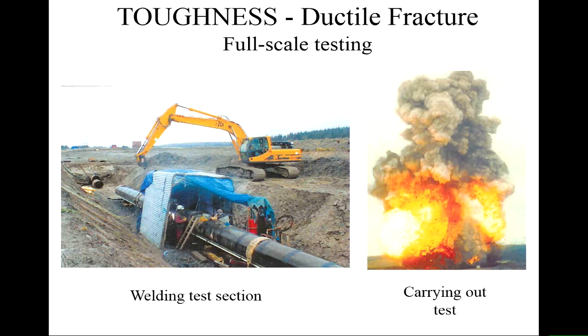So you have a section of pipe here, and end caps can be welded on, a trench can be made. You can match the sort of conditions that you've got for a real case. You can put a defect in, you can apply the stress, and you can watch the explosion when this happens. And then you can go and look at the pipe and see if it did what you thought. You can measure, therefore, crack propagation, and you can measure the damage caused by deliberate explosions in a controlled case in a field in the middle of nowhere where you're not going to hurt anybody.